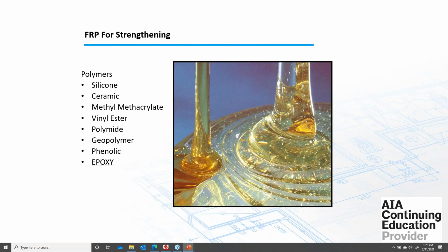For the polymers that we're using to encapsulate these fibers, there's literally thousands of different polymers, but all the FRP manufacturers are using epoxy. We use epoxy because it's got very similar properties to the concrete as far as the stiffness and the flexural capacities and things like that. It just lines up the best. It also adheres exceptionally well to the concrete. Of course, the one downside to that is epoxy has absolutely horrible fire endurance. So you're going to lose the FRP system when it's exposed to a fire. And we'll get into that a little bit later on here.